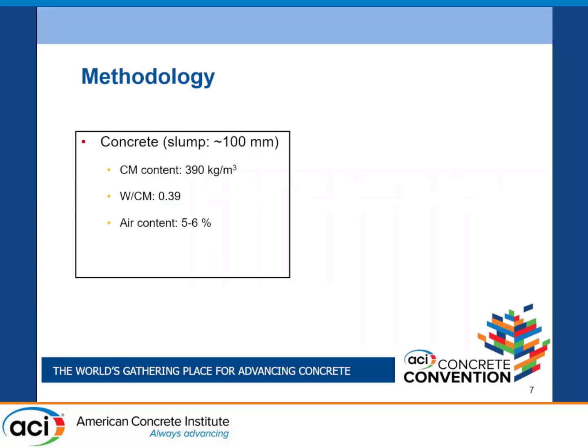For the conventional concrete, we aimed for a slump of 100 millimeters. The cementitious material content was 390 kilograms per cubic meter, with a water cement ratio of 0.39. Our concrete was air entrained, with 5 to 6% air by volume.